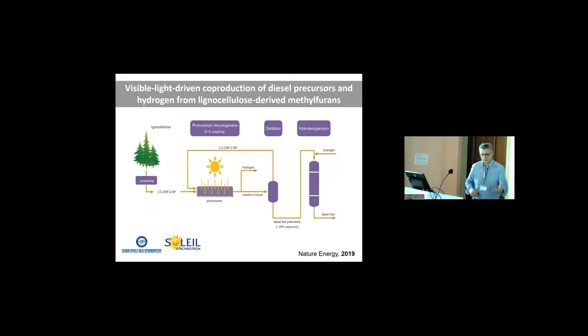Nano is important also in the direction of making more and more sustainable fuels. Here is an example of what we did in collaboration with the Dalian Institute of Chemical Physics, where we try to make diesel in a more sustainable way. So you can start from biomass. In this case, we use methyl and dimethyl furans, a complex mixture obtained from biomass processing. And by a photocatalytic process, which involves carbon-carbon coupling using a ruthenium doped indium zinc sulfide photocatalyst, we were able to get hydrogen and what we call a diesel precursor that can be separated.